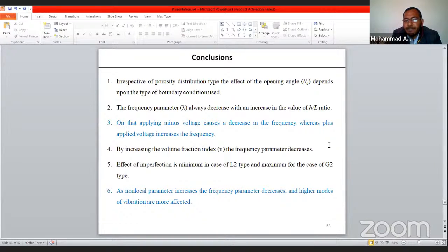By increasing the volume fraction index, the frequency parameter is decreasing. Why is it happening? As I have discussed, by increasing the value of n from 0 to infinity, the metallic content increases. For n equal to 0, the ceramic content is maximum and metal content is 0. In case of 1, it is 50-50%, 50% ceramic and 50% metal. And after 1 to infinity, on increasing the values of n, the metallic content is constantly increasing. Compared to ceramic, metals have lower stiffness. So on increasing the value of n, the stiffness of the structure is decreasing. When the stiffness decreases, then the frequency will obviously decrease by increasing the volume fraction index n.